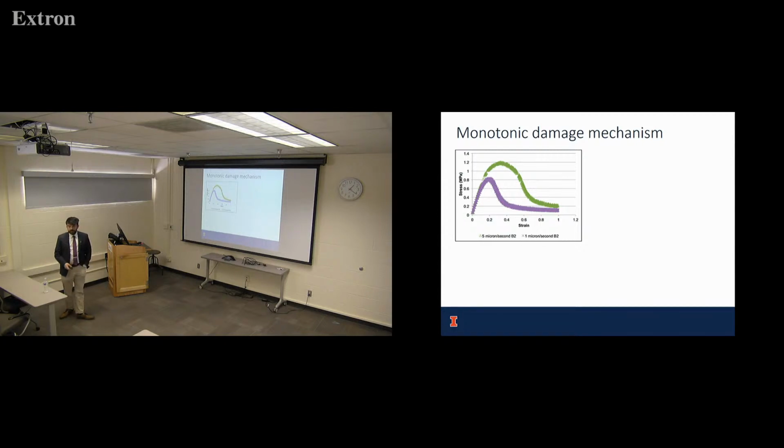And what was happening on the images to that one? So on the images for that one, we didn't see any observable damage really until almost the peak at 80% or so. We still didn't see it even in that plastic phase. So we were thinking that was just deformation, but no damage observable until it did hit peak around 80 and started decreasing rapidly. So then we started to see the damage. That's when we say for sure that there is damage based on the images too.